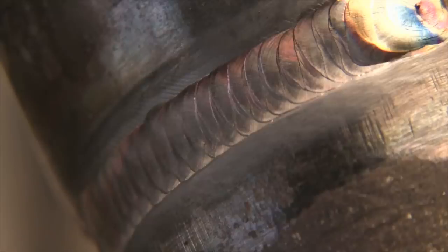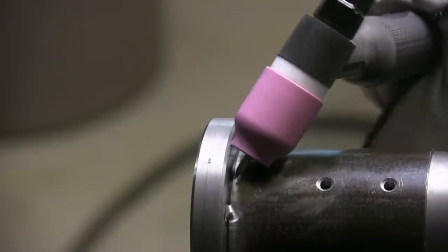This is the second pass doing the same thing, propping with the TIG finger and just not spending a lot of time across the middle because I don't want to suck back the root pass. Could walk the cup on this as well but I like to have the freedom of moving as quickly as I can and not get hung up by anything.